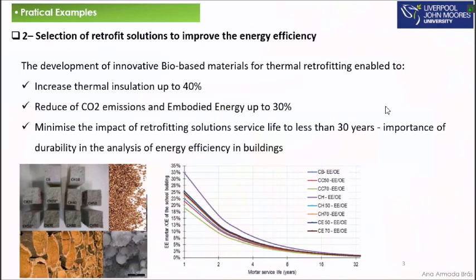We realized that the thermal insulation could increase up to 40%. We realized that there was a reduction of the CO2 emissions and the embodied energy up to 30%. And we realized also that these types of solutions could minimize the impact of retrofitting solution service life to less than 30 years, which highlights the importance of durability in the analysis of energy efficiency in buildings.